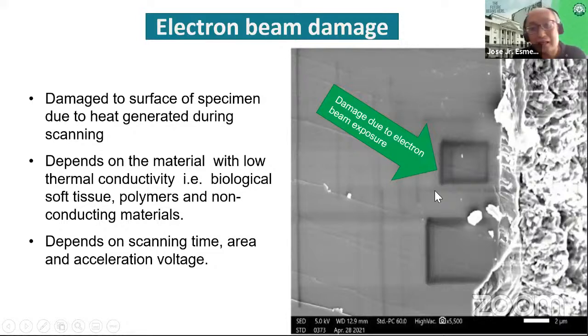So that's why in a scanning electron microscope, especially for very sensitive materials, from the perspective of those submitting samples, it's very important to know whether the sample is destructive or not, and also whether the sample is non-conductive or conductive. This is where we apply coating. Sometimes those asking for analysis will say conductive, but conductive in a way, it's not really. For example, even carbon samples are conductive in a linear way, but the surface resistivity is still very high for carbon, about 1 megaohm. So for that kind of material, it's still important to coat it with metal in order to mitigate sample charge-up or image distortion.